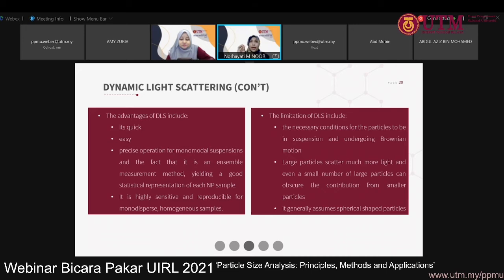For example, if you have a very concentrated formulation, the particles will cause multiple scattering, and we do not want that to happen. So for DLS measurements, you have to dilute your samples so that the particles are really single particles. When the light goes through, it is scattered by each particle on its own. If you have a very high concentration, the scattered light won't go directly to the detector; it just goes next to the particles. So the concentration of your formulation is also important to measure the size of particles.